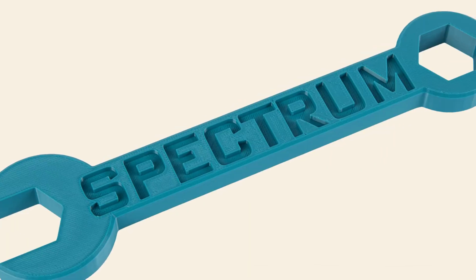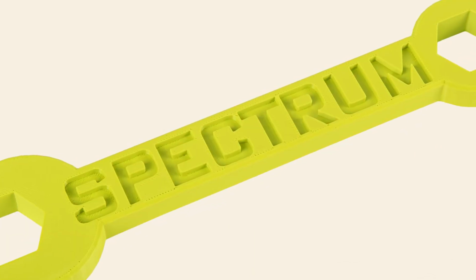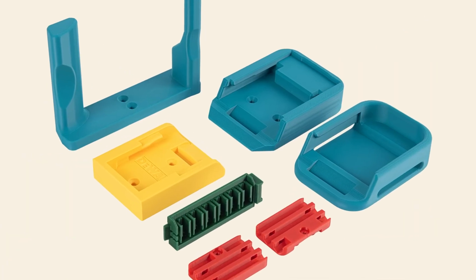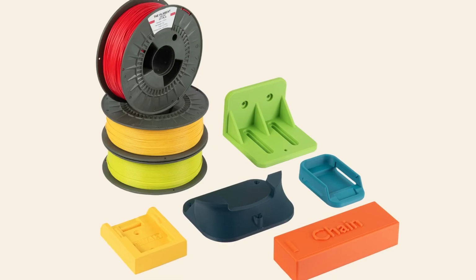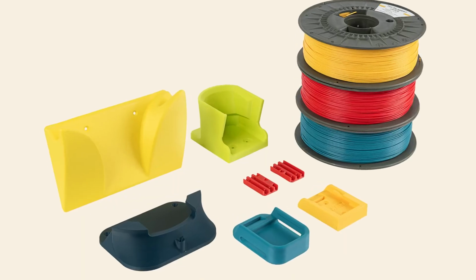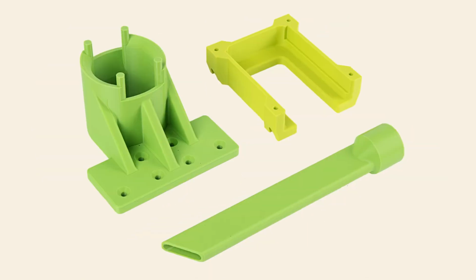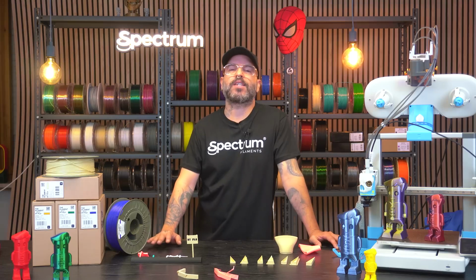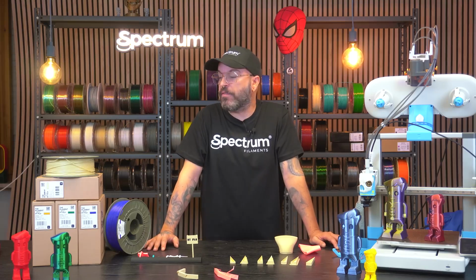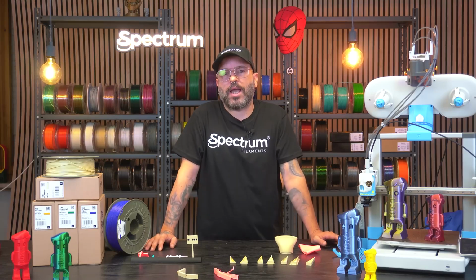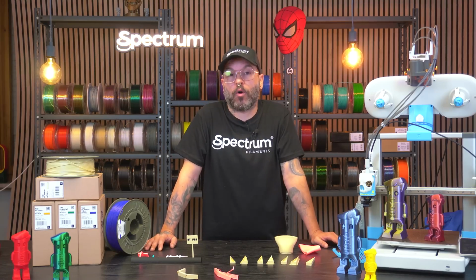By following these tips, you can successfully print HT-PLA parts that are durable, visually refined, and dimensionally stable up to 150 degrees Celsius without the need for any additional heat treatment. Alright, this video was really fun to make and the filament is absolutely great. And you can see in all the tests that we did, it performed great.